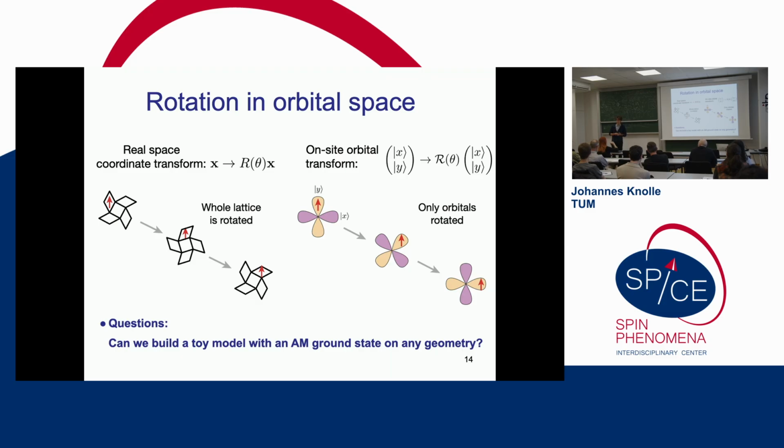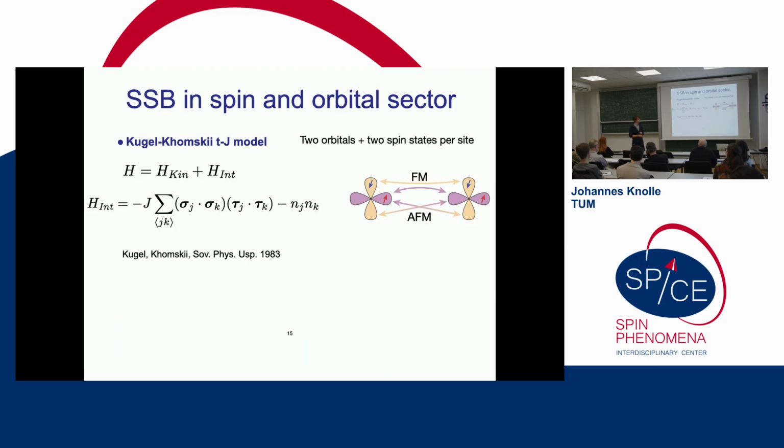Can I ask a question? Yes. In altermagnets, you have these nodal directions and anisotropy, which is an altermagnetic feature, and in an experiment we use it to say whether it's an altermagnet or not. Here it looks like everything is isotropic. So we will see. We will break that spontaneously. Oh, that will appear spontaneously. Yeah. So just like you take a Heisenberg, let's say antiferromagnet, you start completely symmetric, but then it spontaneously chooses a direction. In reality, there's always some single-ion anisotropy and so on, and that chooses it.